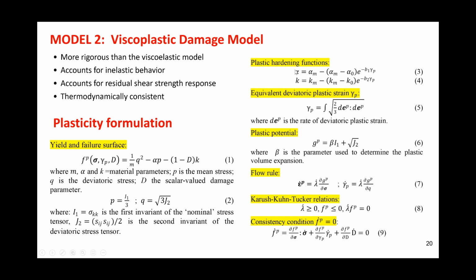The hardening functions are given here. You can see that alpha and K decrease exponentially as a function of the deviatoric plastic strain. We need a plastic potential. In this case, we assume it to be non-associative. And we use simply a von Mises type plastic potential with the main parameter beta. Beta is a measure of the dilative characteristics of the material.